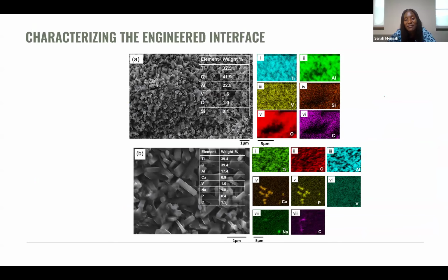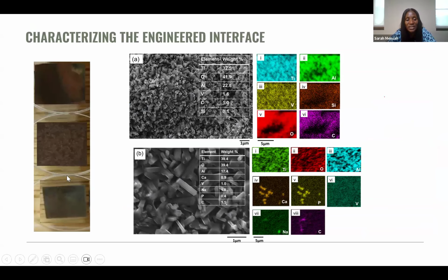Now, as we are thinking of advancing the field, when all of these have been done, we need to be able to characterize the materials to see whether the structure and the properties that we were hoping to see have actually taken place. For instance, the material that I coated, this is it, and this is how you see it with the physical eyes, but with some advanced characterization, we're able to really see the structure. This thing that we just see as some dark material, upon characterization, gives us the structure of the material. I mentioned that for implant material, we needed to have some topographies and some chemistry. Our characterization in the lab is able to tell us that indeed, this material has grown some nanorods, which make it that desirable topography. And when we check the elemental properties through EDS, we're able to see calcium and phosphorus on it.